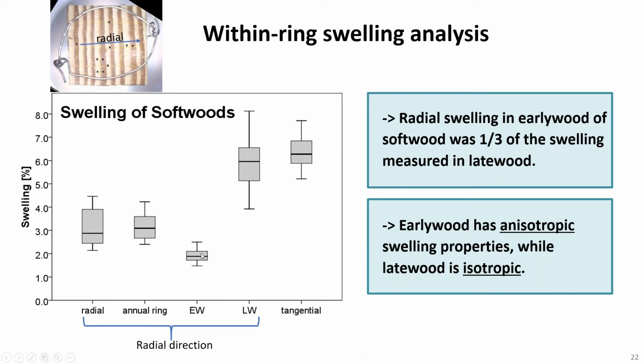Whereas in the early wood and late wood the difference is big, so the anisotropic behavior is there, within the late wood we see more isotropic behavior. This is interesting because there is more movement in the late wood than in the early wood. That's not something we would have expected because there's a great density difference. But of course, that's also the reason why it creates internal stresses. When you have those data, you could calculate those internal stress developments.